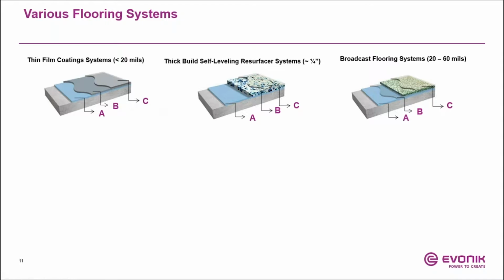One is thin film coating systems. In this case, the total system is less than 20 mils. So a lot of times what you're doing is using very thin films to apply over concrete. When you have a very smooth concrete floor, you don't need to apply very thick coatings. And in many cases, these are water-based systems, because with water-based systems you're generally applying at less than 5 mils.